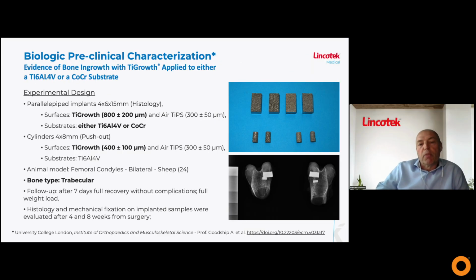In this experiment, performed some years ago together with University College London, TiGrowth was applied on two different substrates, titanium 6-4 and cobalt chrome. The TiGrowth applied was in the high thickness, 800 microns, and for control, air plasma spray titanium at 300 microns was also applied. The animal model was sheep, and the bone type where the implants were placed was trabecular bone in the femoral condyle. The follow-up immediately after surgery was good, and the histologies and mechanical fixation were checked at 4 and 8 weeks after surgery.